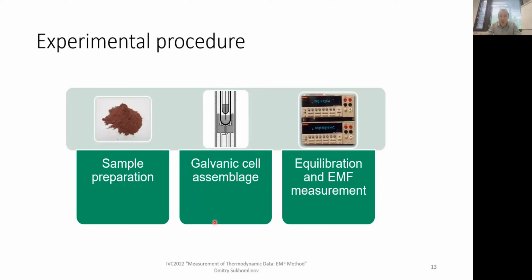A few words about the experimental side, experimental procedure. It usually starts from sample preparation. Often we cannot purchase those phases we are interested in to investigate, to measure Gibbs energy of formation. So we first need to probably synthesize them. Or at least we mix certain phases, which are going to be our equilibrium phase assemblage generating equilibrium oxygen partial pressure at elevated temperature.